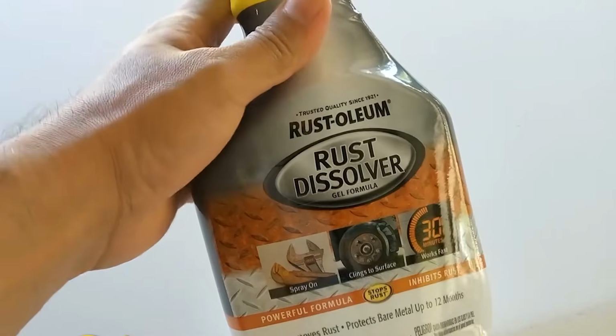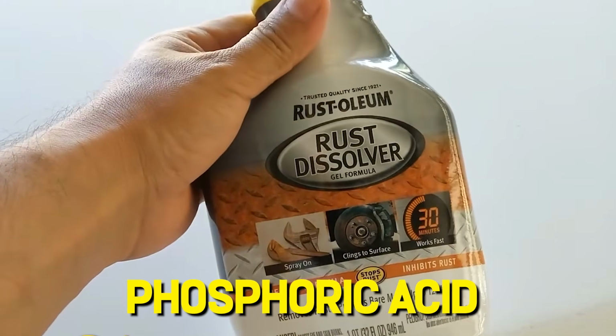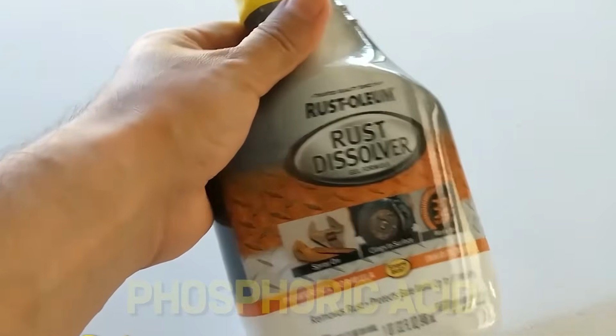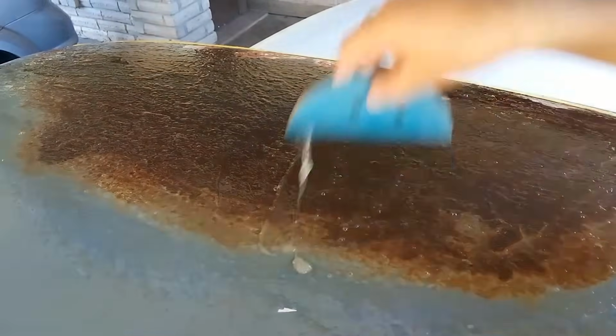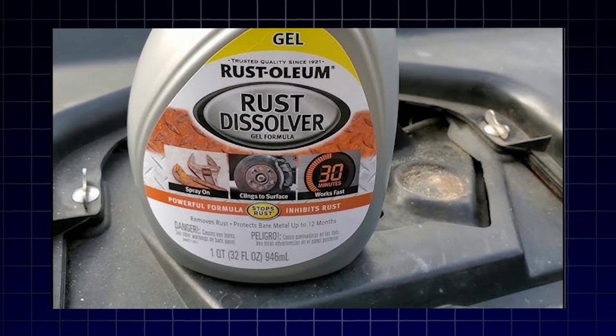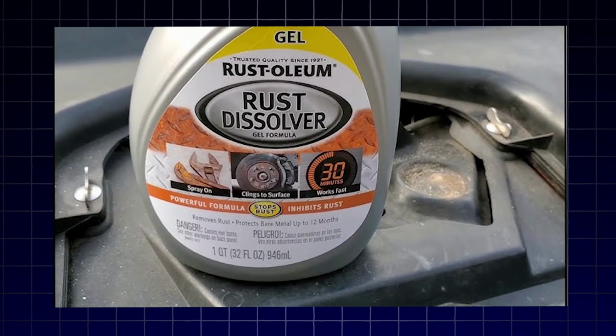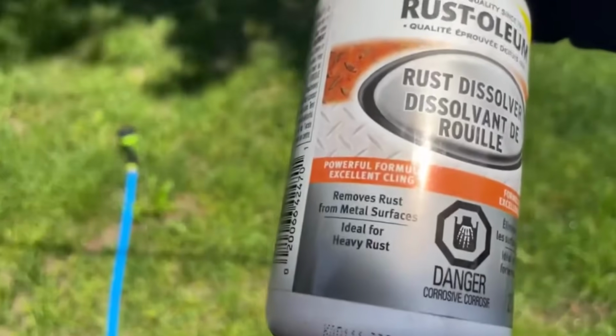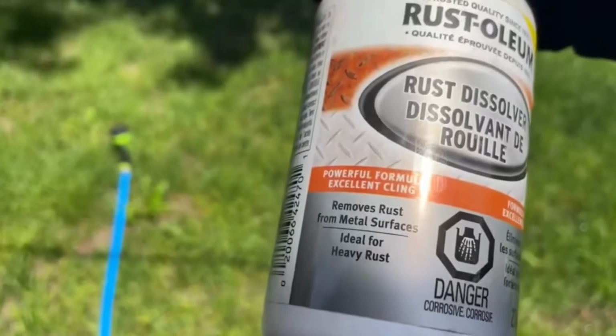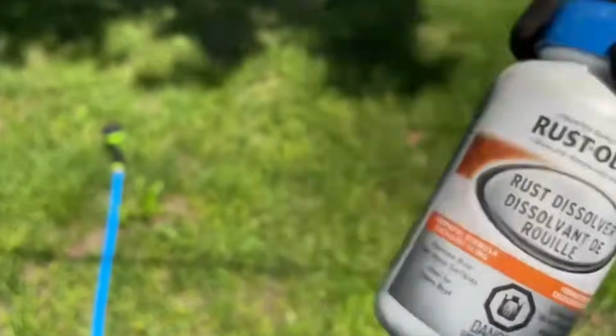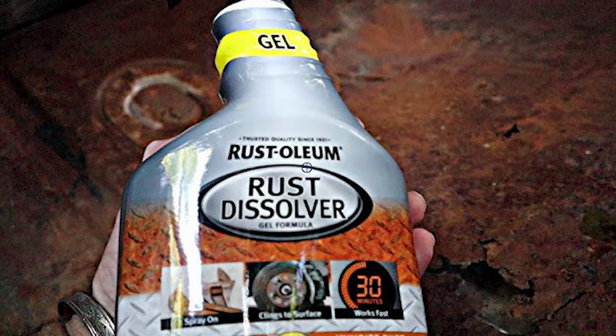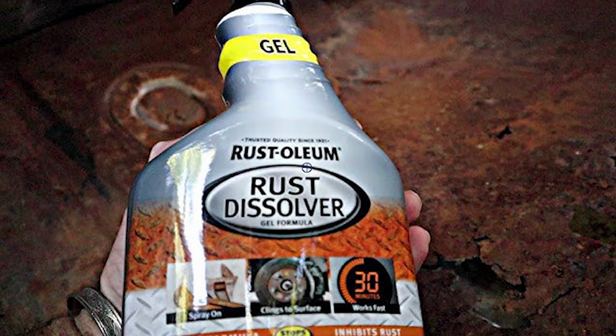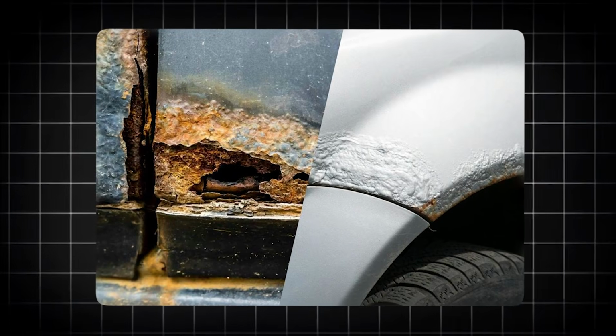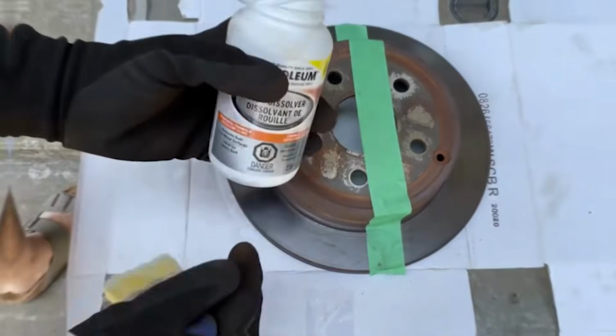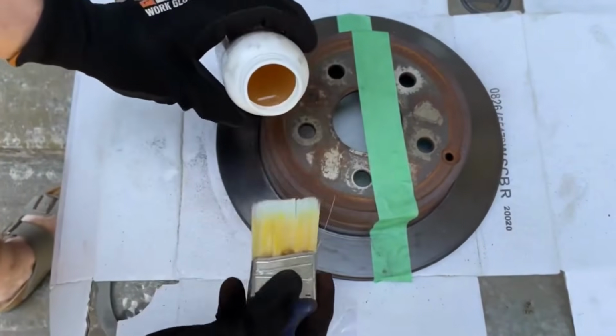This conversion reaction is what makes phosphoric acid products genuinely suitable for vertical and overhead frame applications. The gel formula clings to vertical surfaces long enough for the acid to initiate the conversion reaction. In our testing, the Rust-Oleum Rust Dissolver Gel produced visible surface conversion on light and moderate rust within the contact time the gel formula maintained on vertical surfaces. The treated surface took on the characteristic dark gray appearance that indicates iron-phosphate conversion has occurred.